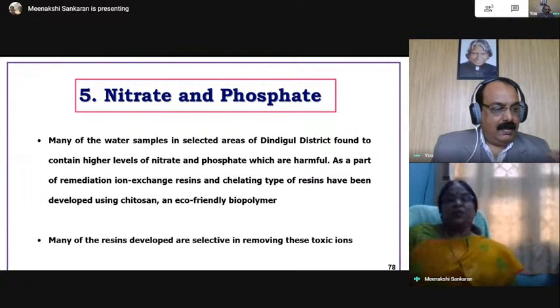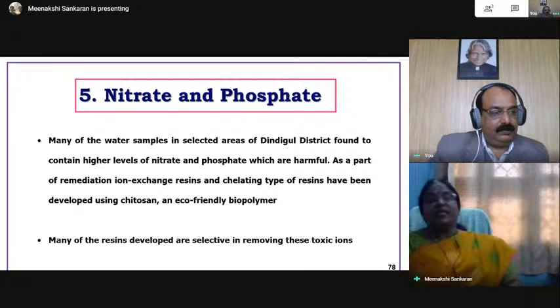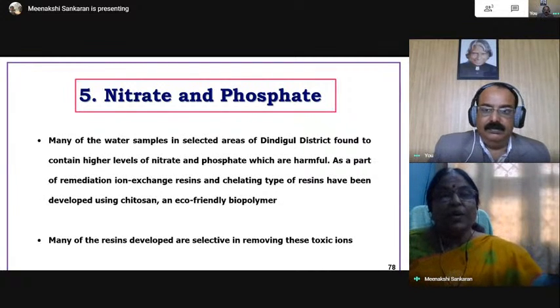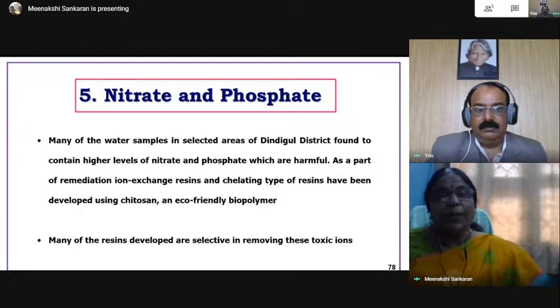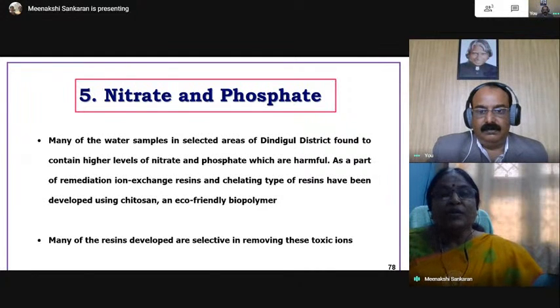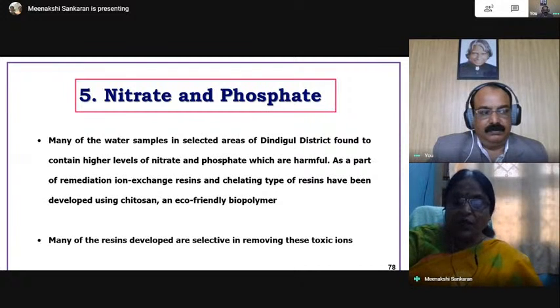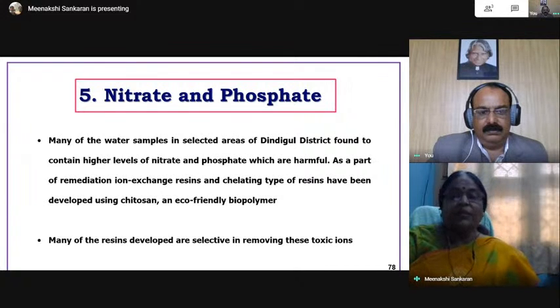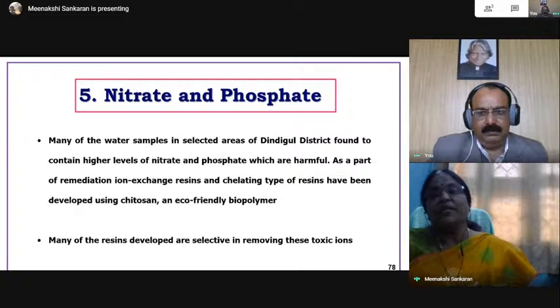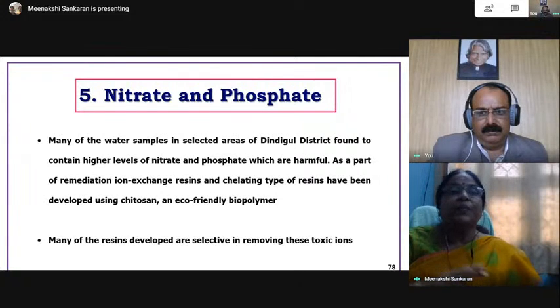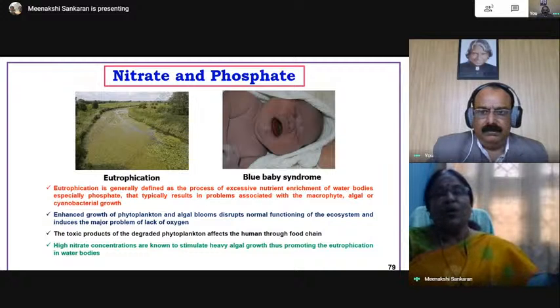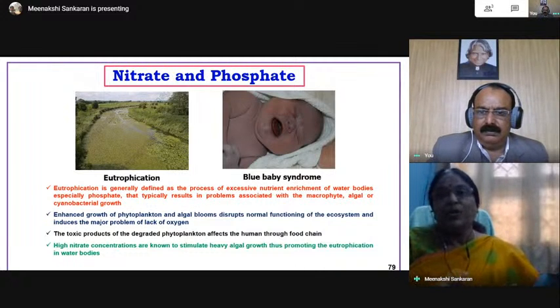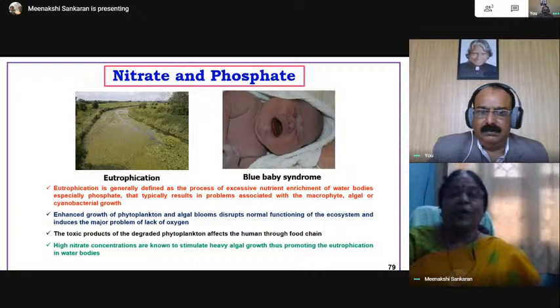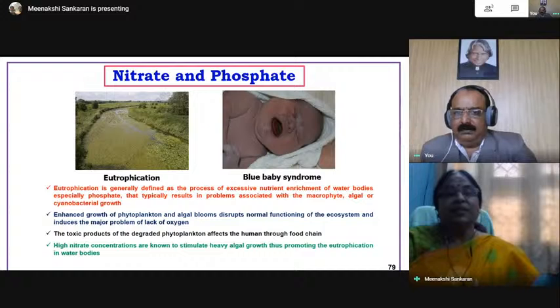And then nitrate and phosphate. Many of the water samples in selected areas of our Dindigul district were found to contain higher levels of nitrate and phosphate. So we have gone for this research also, that is, removal of nitrate and phosphate from drinking water. Many materials we have tried, and I am highlighting only the sustainable materials made out of chitin and chitosan. Clear water is called oligotrophic. That is, it is very clear. Then it becomes contaminated with nitrate and phosphate.